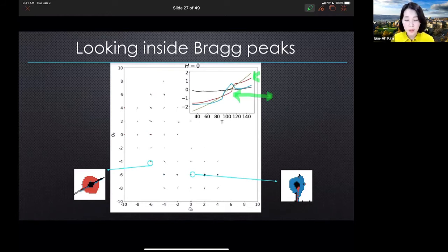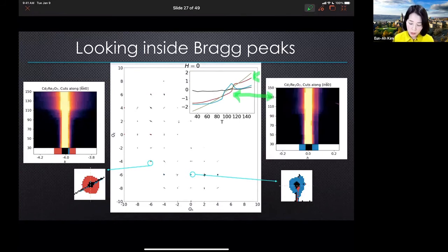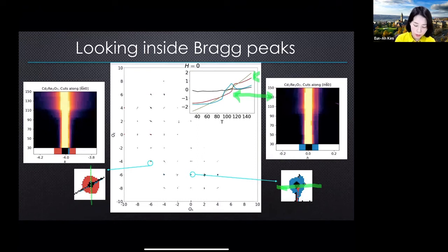But for my experienced X-ray specialist colleagues to believe this to be real, we had to look at the raw data. So what I'm showing here is the cut along this line and along this line for these two different clusters. And you see indeed the red diffuse region. The center here is the center of the peak, but the diffuse region is showing this intensity all throughout phase two. And the blue region, relatively speaking, is showing much weaker fluctuation, but then shows enhanced activity at the lower temperature phase. So when we figured out we can think about this clustering result by looking at the raw data, that's when everybody was on board that this is real. And then we started trying to understand what's going on. And then it occurred to us, this is of course right.